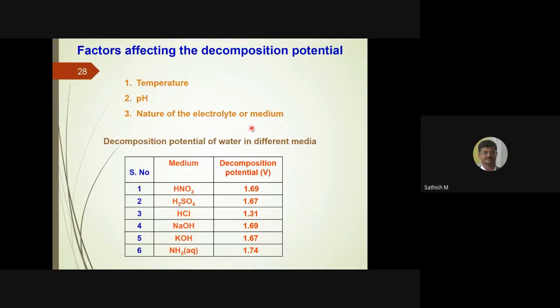These are the various parameters which affect the electrolysis of water, like temperature, pH, and what the medium is, alkaline or acidic. I put the various voltages for the different media. If you see hydrochloric acid, it looks like 1.31, but chlorine will evolve on the other side. Chlorine is very corrosive, particularly nascent chlorine when it forms. Most electrodes may not be stable in this medium. So even though this process looks low overpotential, generally it's not viable for commercial production.